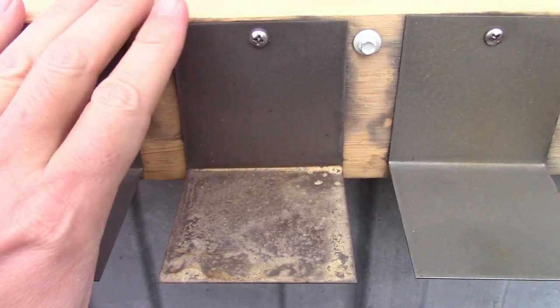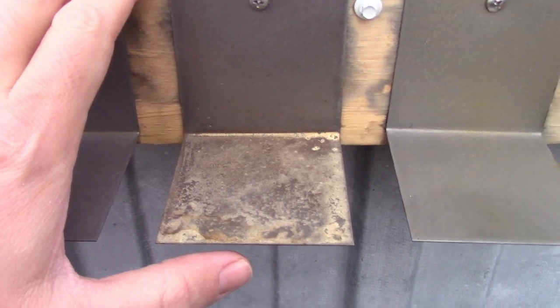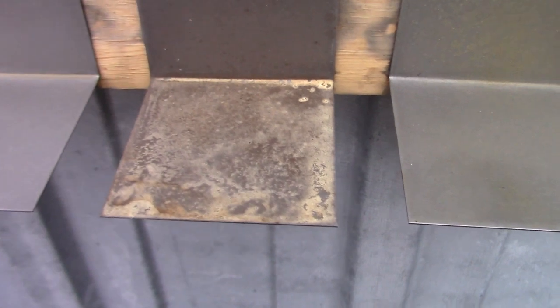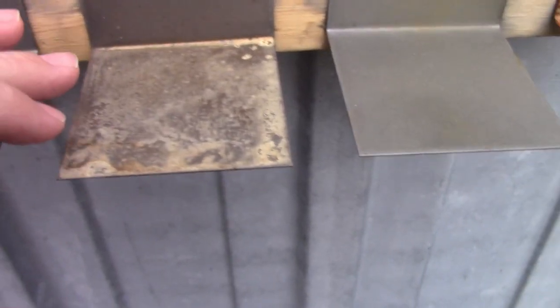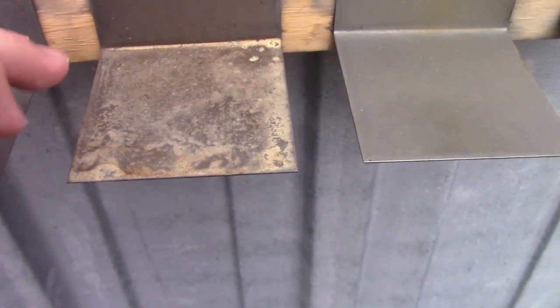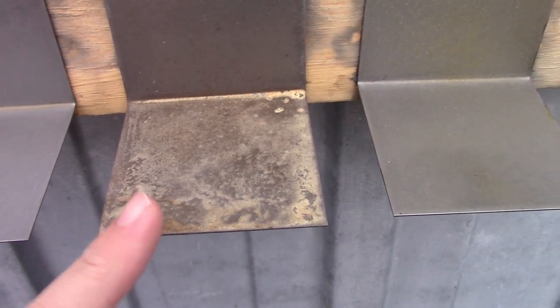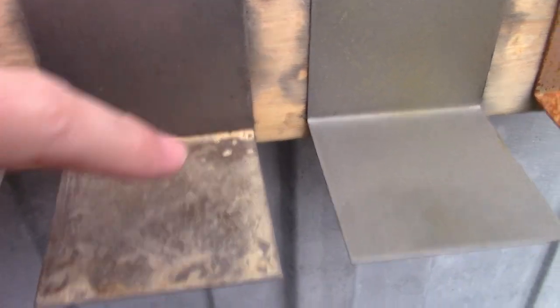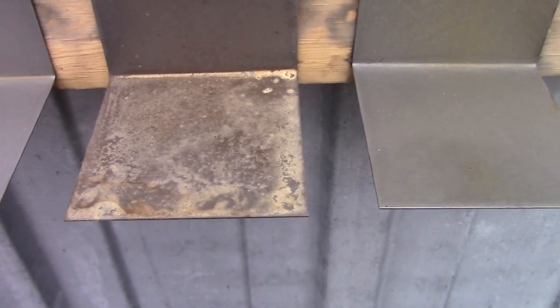Moving next door to the Bow Shield — this is probably the most striking difference of all the samples. The horizontal surface is very discolored, and I don't believe it's rust. There seems to be a nice film on here, but the film has actually started to dry out and flake off. This is one that remained pretty liquid and very wet, so this is a pretty interesting outcome. You can really see it in the corner — it's just starting to flake off and get blown away by the wind.